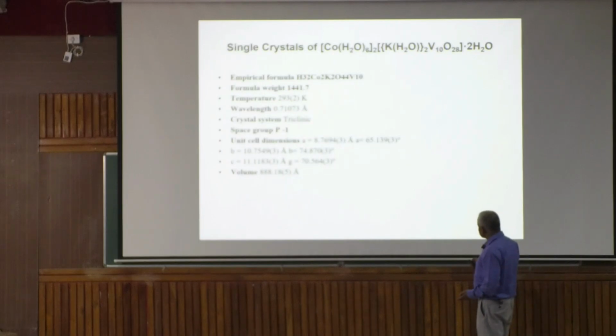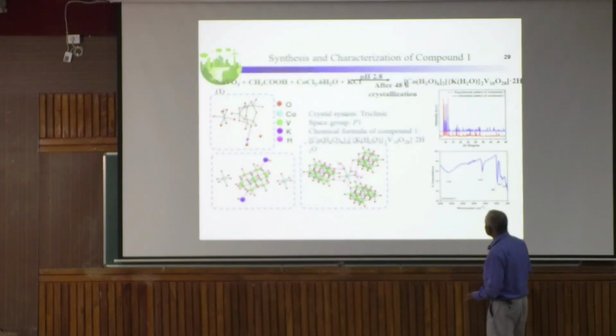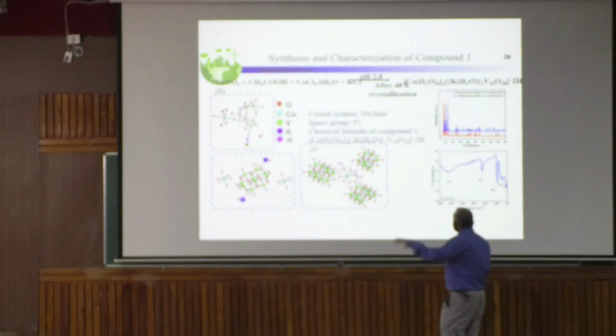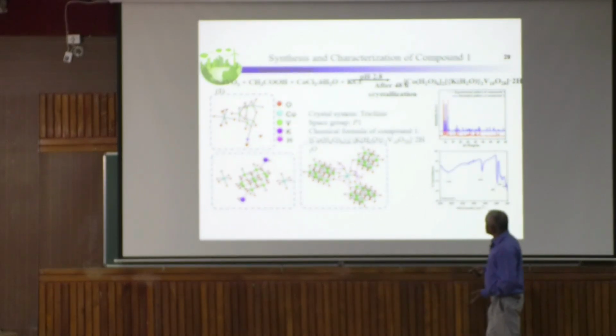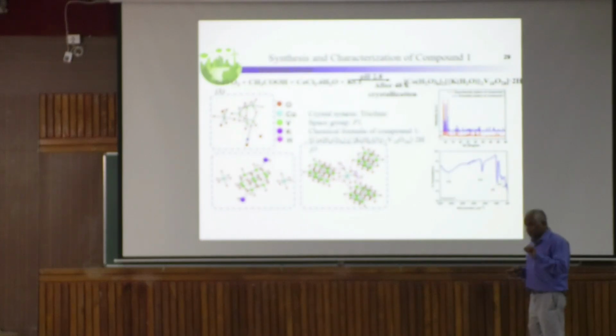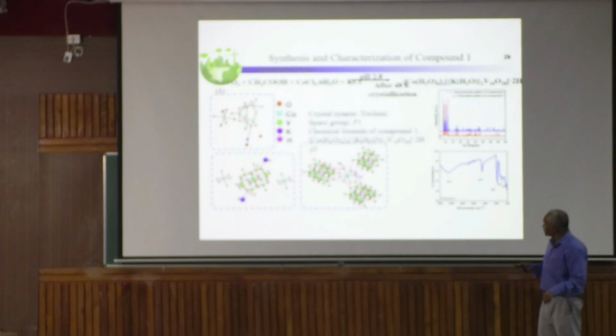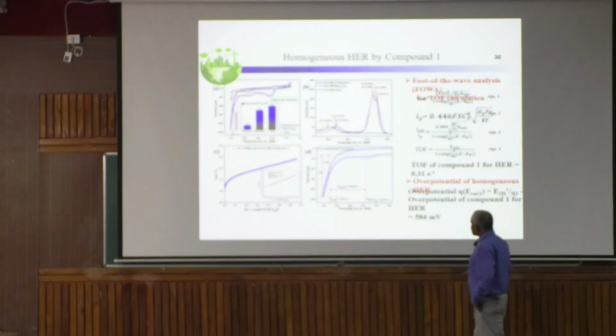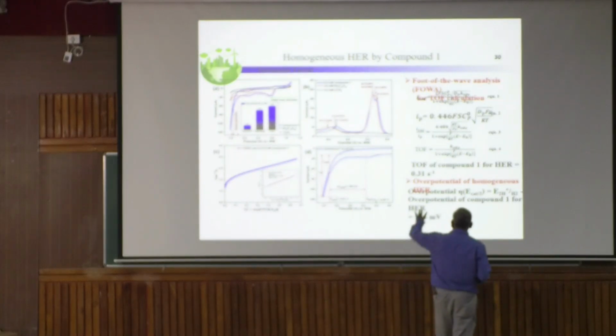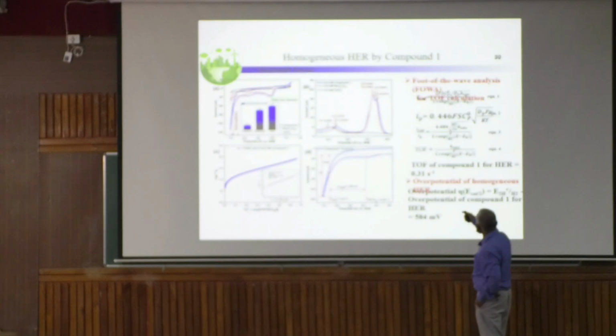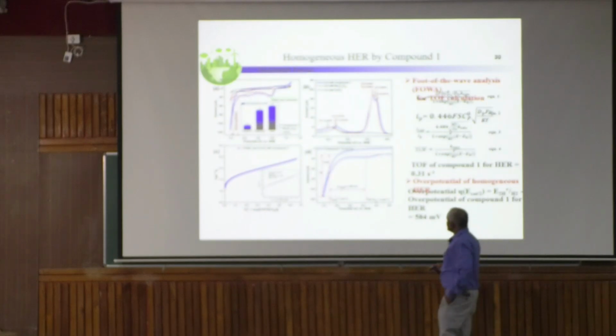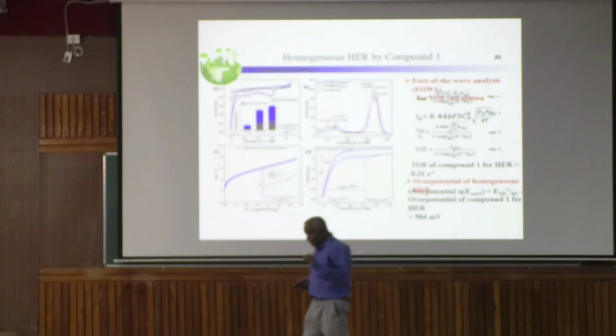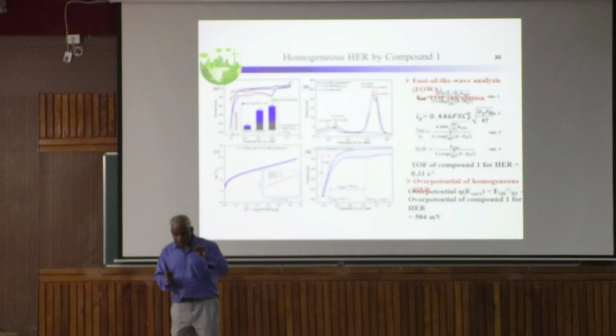So these are the crystal parameters. I just took it from there. And then we did a lot of study, Raman and crystallography, PXRD, telling that everything is fine. The only thing we proved is that whatever solid state is there, in solution it remains the same hydrogen bonded structure, we checked by mass spectroscopy. Then we did the electrocatalysis. I will not go through all these details. We wanted to tell you that a synergy between cobalt and decavanadate is established, and that synergy does this job.